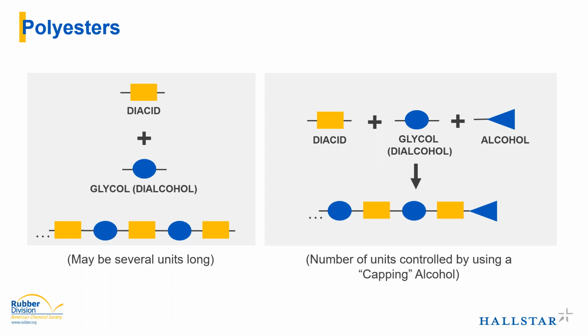On the right side here, it just shows with an alcohol, but this can also be done with the acid, that we can mostly have diacids and dialcohols or glycols, but we can also add a small amount of monofunctional alcohols to cap that chain and stop it from reacting any further. And that gives us unique properties for the chemistry of the end caps of the chain, but it also helps us to control how long those polymer chains are by adding a certain number of those monoalcohols to not allow them to get any bigger. On the other side, we can not add those and allow the chains to just get as big as possible to really raise up that molecular weight, which can be really useful in certain applications.